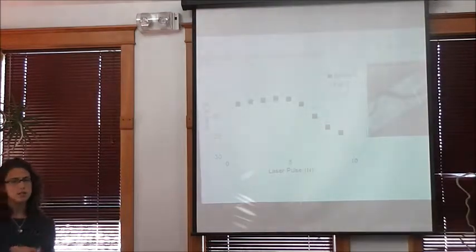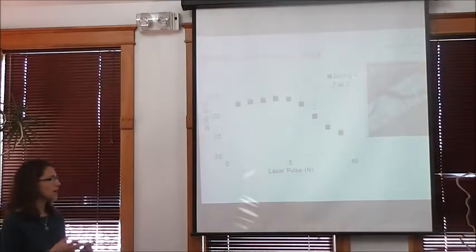And so you can see that throughout the scale, starting from the surface and then drilling down to the very bottom of the scale, we see quite drastic differences in the carbon isotope ratio. So while we didn't see any differences on the surface, in drilling down through the scale, we saw drastic differences. So this means a couple different things about the scales. The first is that we thought the scales were a more static record of the conditions that the fish were being exposed to. We thought they were a fairly reliable record of the food that the fish was eating. However, it seems that these fish in times of stress or starvation are actually resorbing some of the carbon that they've stored in their scales and remodeling the scales a little bit. So these scales aren't quite the static, reliable record that we had thought.